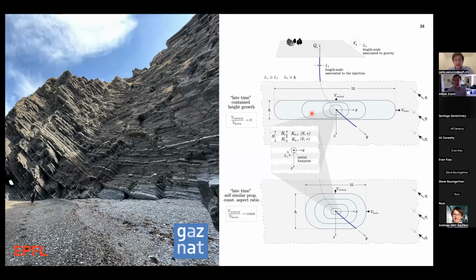Yeah, that's another interesting point, and it goes along with the comments of Danesi before. Well, in this case, what I would expect is that you will have a slowdown of the growth. So in this scenario that I assumed, with linear elastic fracture mechanics, the Young's modulus is the same, and this makes the evaluation of the stress intensity factor at the interface much more tractable, I would say.